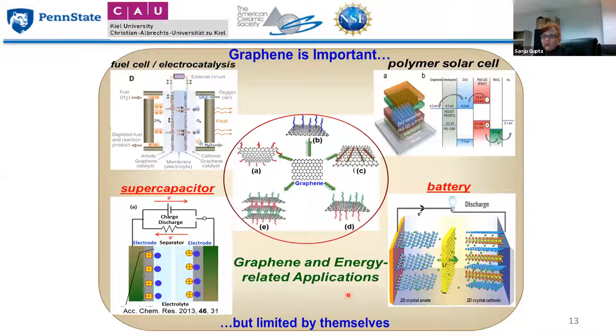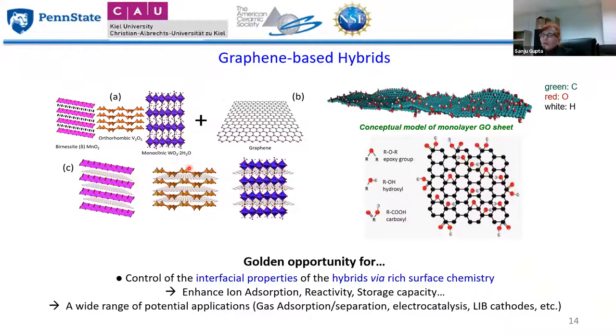So graphene is important, either by itself as an active electrode, or as a support system. You can decorate that graphene surface, depending upon the functionality, with other nanomaterials, and that's what I'm going to show you. Graphene can also be used for polymer solar cells and fuel cells, as I mentioned before, but they are limited by themselves. So how do we enhance them? We make graphene-based hybrids. That's a golden opportunity because we can control the interfacial properties through the rich surface chemistry of the graphene, both basal plane and edge sites. So we can play around, and it really provides a rich playground to form these exotic graphene-based hybrids for these applications.